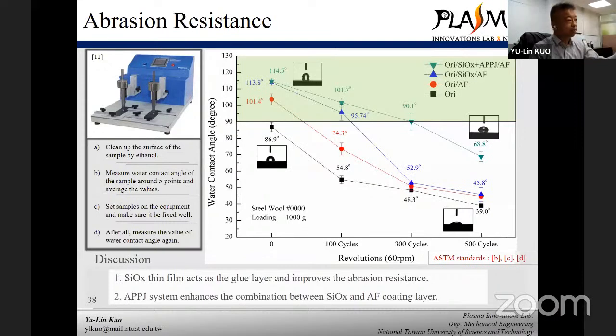So you can see the contact angle will dramatically decrease to a quite lower value, which means that the surface has been roughened because the abrasion resistance is not so good. But if you just put the anti-fingerprint onto the original sample, you still can have a hydrophobic surface. However, once you try the abrasion for 100 cycles, it will fail because the 90 degrees cannot be achieved. So this is not a good one.